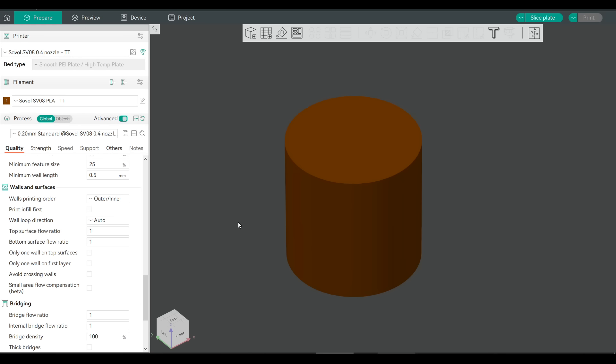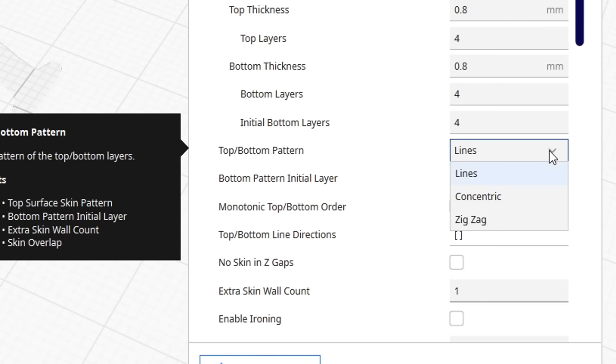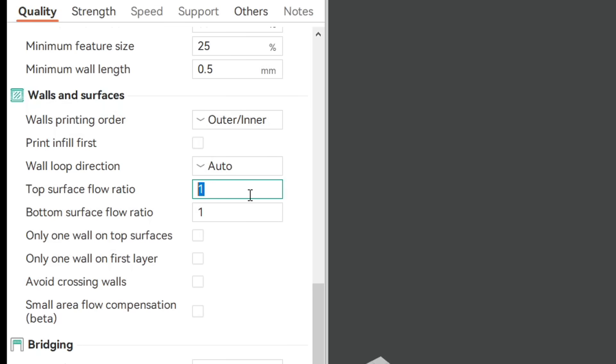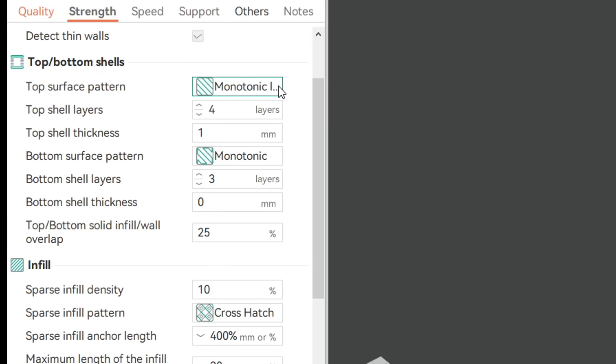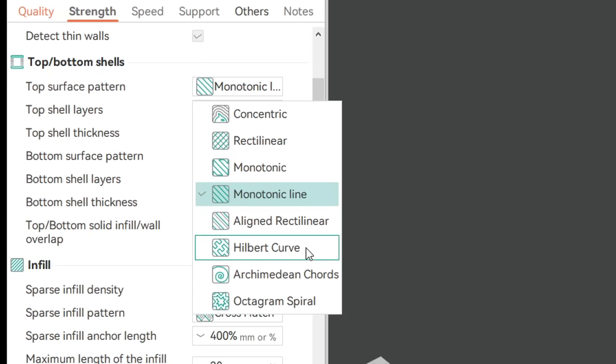Both of these, are in Bambu Studio, and Orca Slicer, but PrusaSlicer is no good, because we can't adjust flow, only for the top layer, whereas Cura has this, but lacks sufficient options, for top infill pattern. Matt's suggestion, was to massively over extrude the top surfaces, with a flow ratio, of 170% or 1.7, and then select, a different top infill pattern, his suggestion being Archimedean chords.